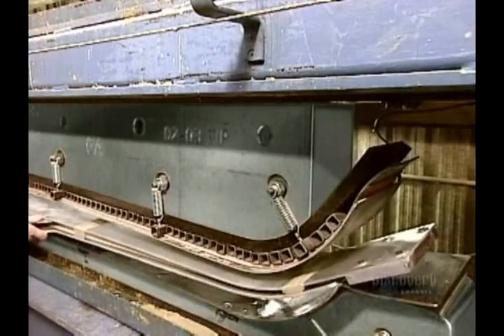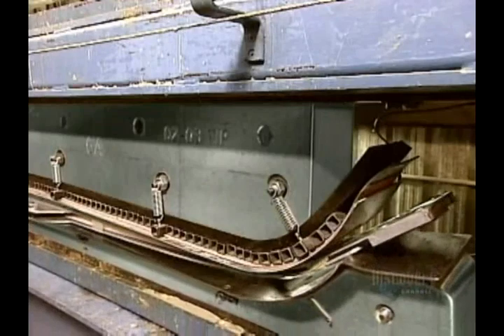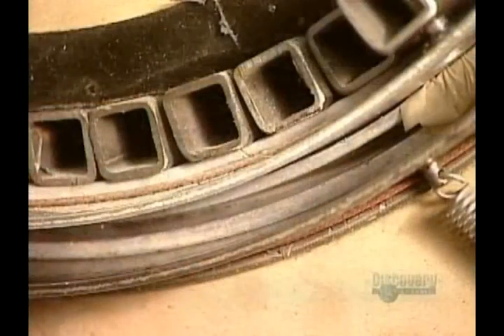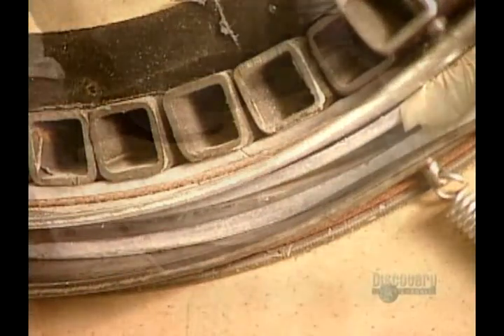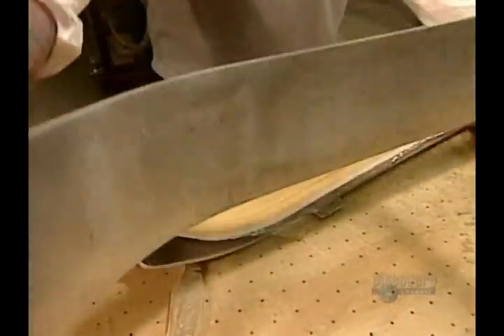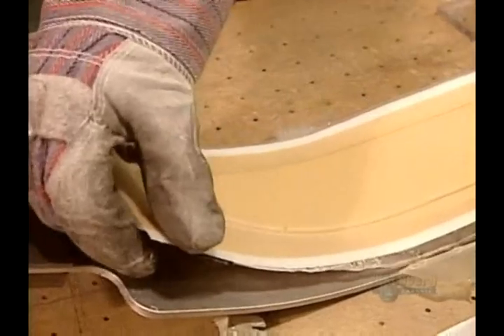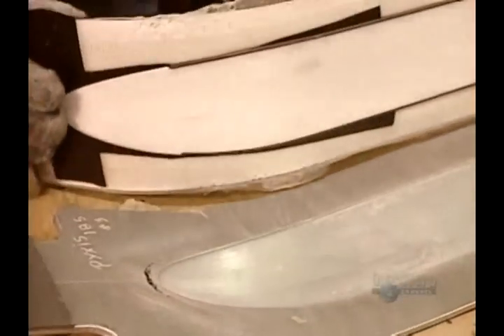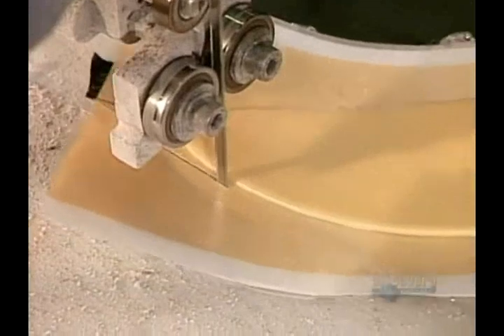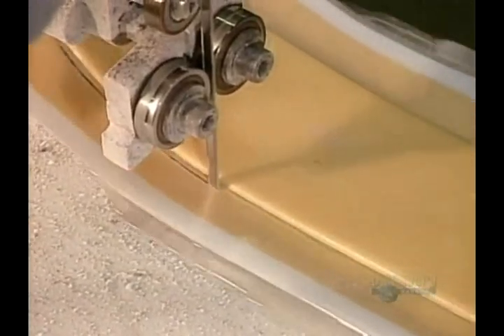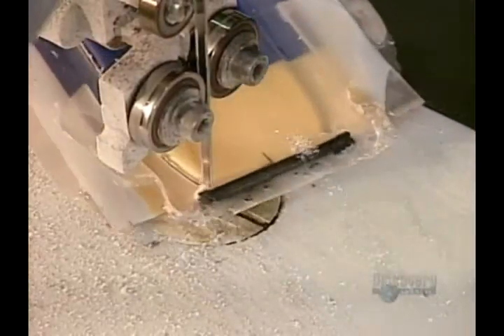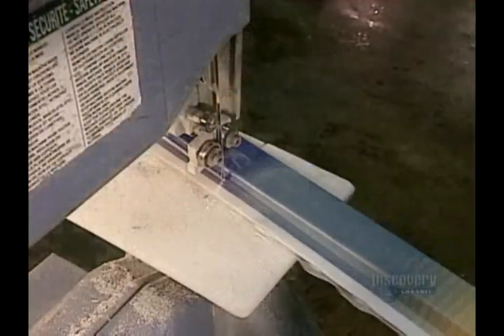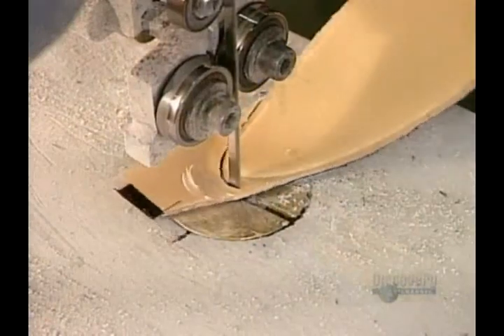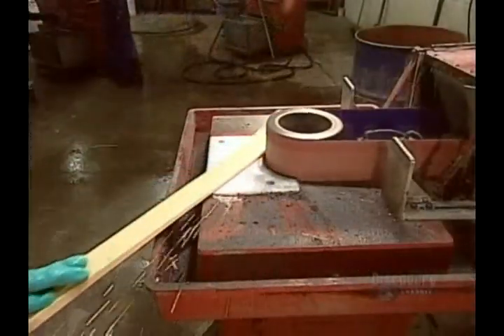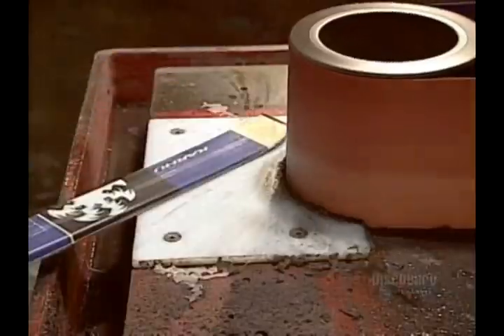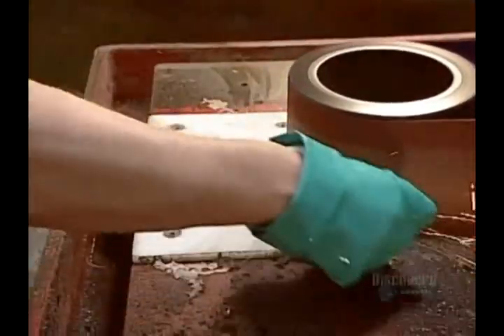Then it's into a press that compresses the mold and heats it to 85 degrees Celsius. This activates the epoxy, hardening it in 12 to 15 minutes, depending on the thickness of the ski. Now they do a rough cut to trim off the excess. Then they sand all the edges until they're smooth.